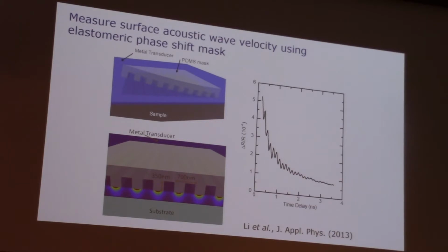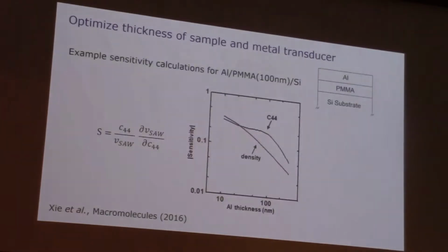But essentially, the point is we can do a pump probe measurement in our conventional optical measurement equipment. We can measure these oscillations in the time domain. We can get the velocity of the surface acoustic waves that travel across the surface, and we can extract elastic constants of materials this way in a quite convenient method, to complement some of our other techniques on longitudinal modes.